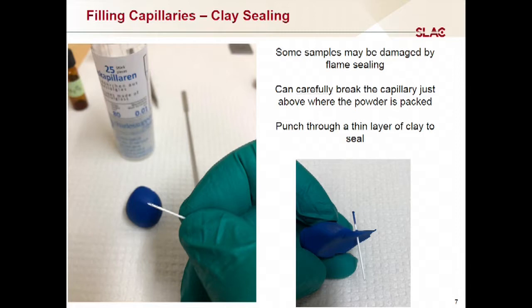And what I have found to be the easiest thing is if you take the clay and sort of pinch it into a thin layer, and then instead of digging the capillary in and trying to scoop out some clay, you just punch it all the way through that layer. And I've done this a few times, so each one would have given me maybe a fifth of this amount of clay. But you punch it through and you leave a little plug of clay inside of the capillary. You can punch it through again and you double the amount of clay that you have. And then you keep doing that until it's basically pushed up against the end of your powder bed.